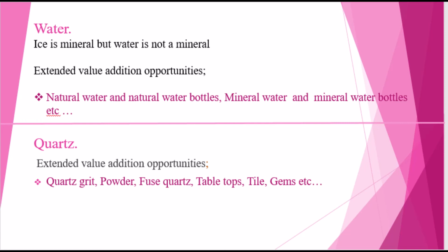So our value addition margin is very high, but we have to think about energy cost, and the capital investment is a little bit bigger, as well as the purity of quartz being very high. We have to upgrade it to the 99.9995 level if we are going to make chips or electronic items.